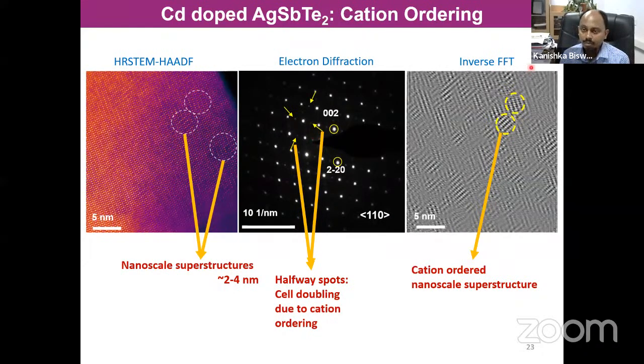And when we have done more image analysis by inverse fast Fourier transform image of this, by only selecting this superstructure spot, you can see clear domains of atomic ordering in this compound, which is the size of 2 to 4 nanometer. Now, previous phonon calculation in this compound AgSbTe2 tells that the phonon mean free path in this compound is of the order of 1 to 10 nanometer, or rather I could say specifically 1 to 6 nanometer. So these ordered domains will scatter hugely the acoustic phonon in this compound, and it will decrease the thermal conductivity, while also enhancing the electronic transport by delocalization of electronic state.